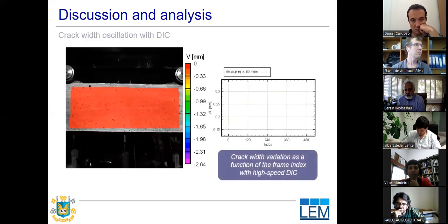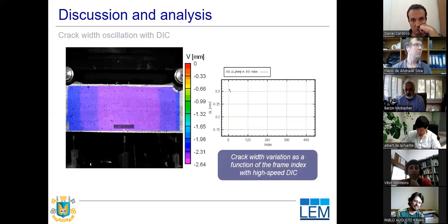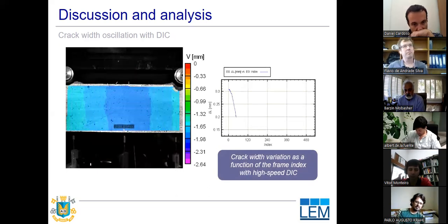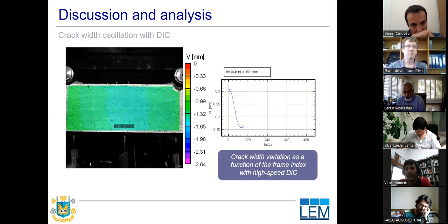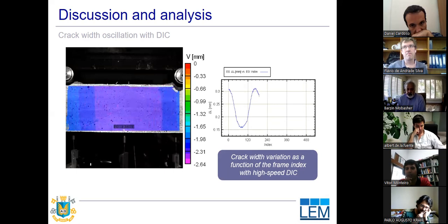And here we have a small video showing the oscillation of the major observed crack on both beams, with and without fibers. So we can see how the crack is oscillating along one of the cycles, one of the triggers we did in the lab. It's oscillating between 0.30 and 0.15 millimeters. We could evaluate that with the digital image correlation system and the high speed cameras.